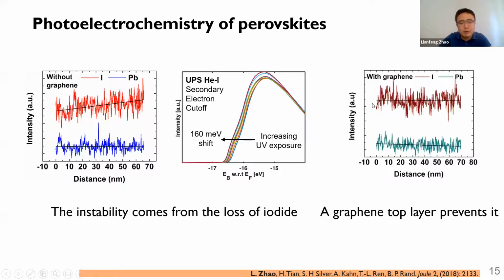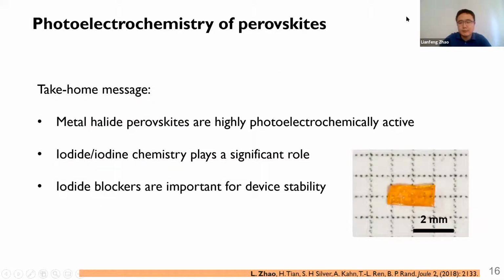What we found is that we can overcome this issue by using an iodide blocker layer. In this case, we apply a graphene top layer on the perovskite thin film. And we found there's no iodide loss, which means that we provide an important strategy to improve the stability of perovskite thin films. So for this part, the take-home message is that the iodine chemistry plays a significant role in device stability, and we should pay attention to blocking iodide diffusion and iodide loss.